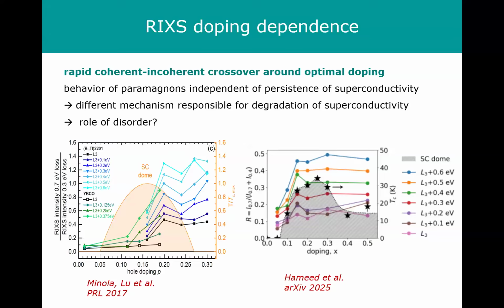And then if you look at a plot like this, the charge order now is really having to do with the ordering of oxygen vacancies, yet superconductivity continues. So how sure can we really be about the doping level, how you quantify it down there? You were showing some optical data. What about X-ray absorption? Or, ideally, maybe photoemission, just to look at the volume of the Fermi surface. Yeah, ideal would be photoemission, of course. But I do understand that doing photoemission on films is challenging. But that would be ideal, of course.